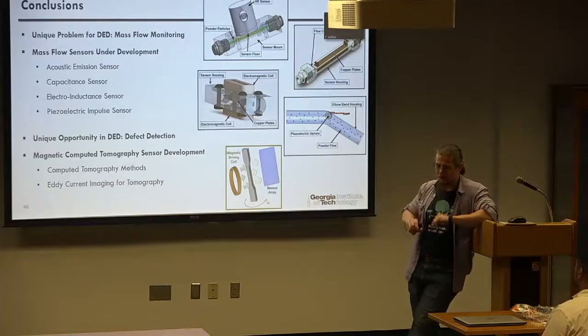Basically, right now, we put a scale in there, we put a cup on the scale, we blow some powder into it, and we calibrate the system right before we print, and we calibrate it after, and we hope we stayed between those two for the whole print. That's the way we do it right now. So right now, there's no actual feedback control. There's no quantifiable measurement of mass flow. We have RPM, and that's it.